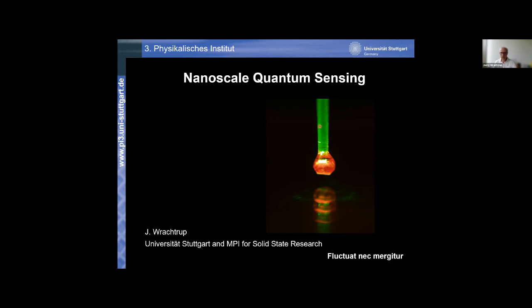What you see here on the first slide is a mock-up of the type of sensors we often work with. What you see here is this reddish blob. In this blob there is a micron-sized diamond, which is doped. This is why it generates red fluorescence if you excite it with a green laser, like 532 nanometer. This is a fiber onto which we have glued this nanodiamond. Essentially, the sensing we are doing depends on detecting the intensity changes in this red fluorescence. This is the observable in our experiment.